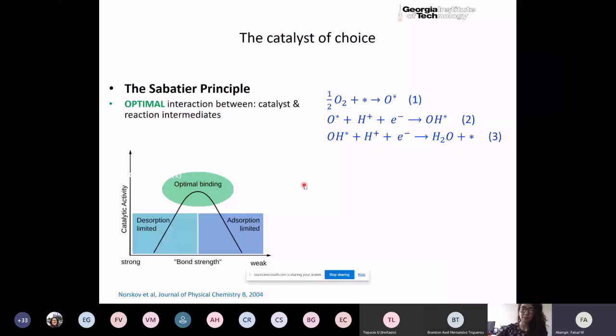Now, when you look at a reaction like the one that's highlighted here, this is the multiple steps of the so-called oxygen reduction reaction. That is a very key reaction for a fuel cell. In that oxygen reduction reaction, you find that there are different types of catalysts that we could be using. And this is a schematic, but the data points here are based off of this paper by Norskov back in 2004. And for this oxygen reduction reaction, we could try different catalysts, and we can see that if we try something like nickel or iron, then the oxygen adsorption part of the reaction is too strong, and so the reactants don't desorb fast enough. On the other end of it, if the adsorption is too weak, then we don't have sufficient activity for the material.